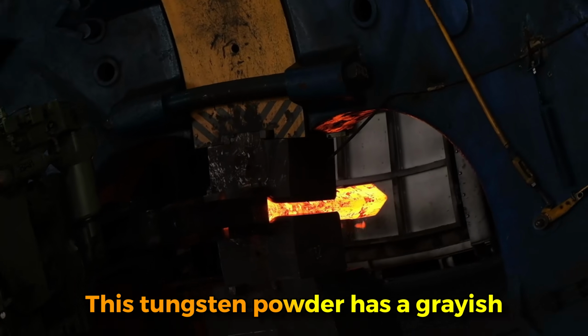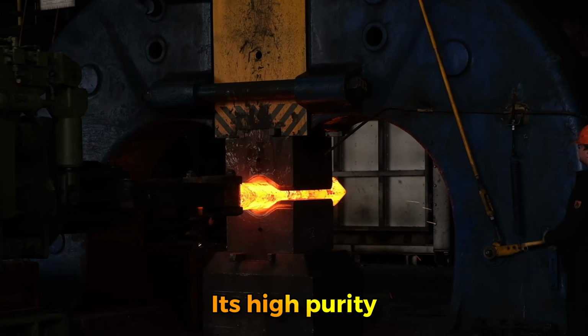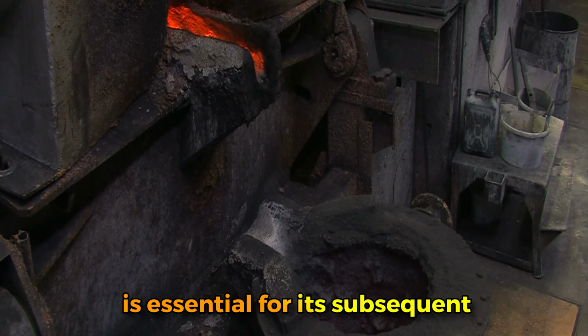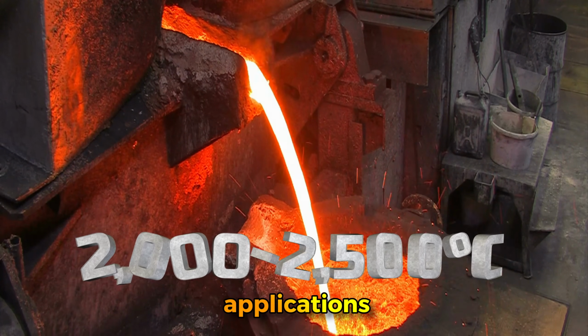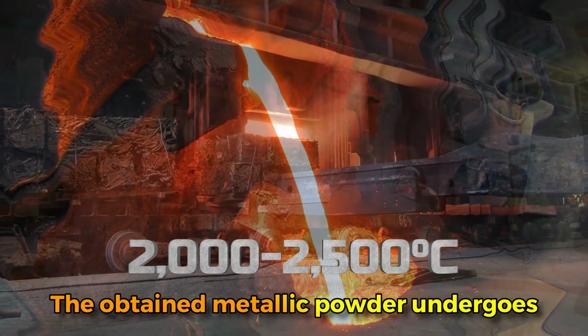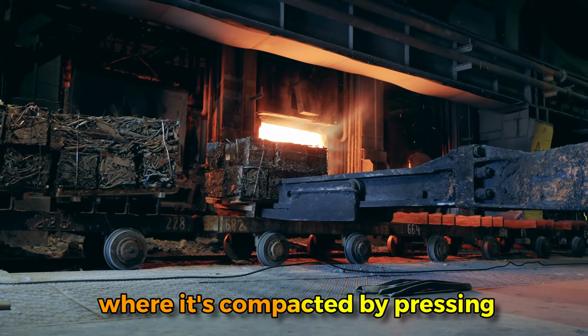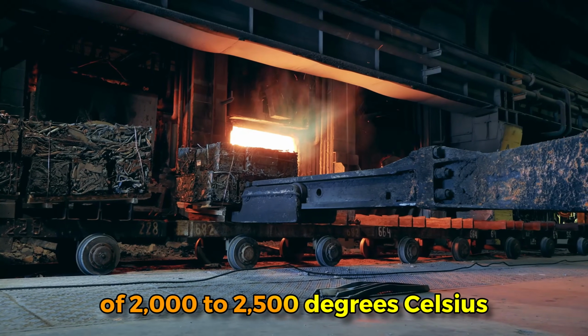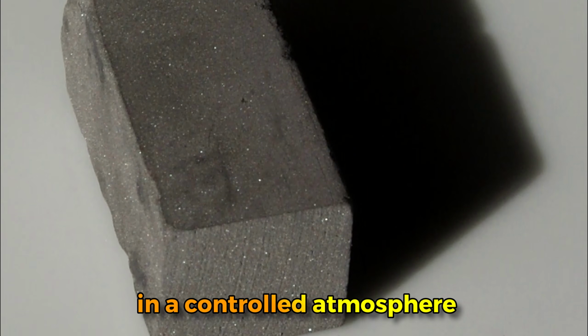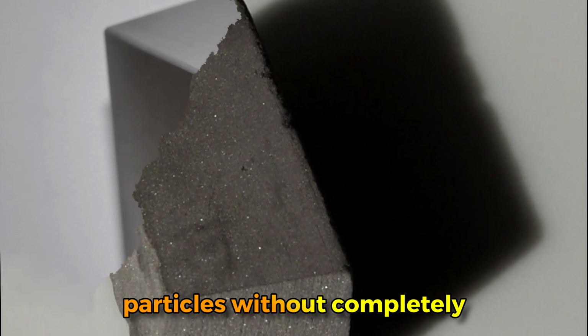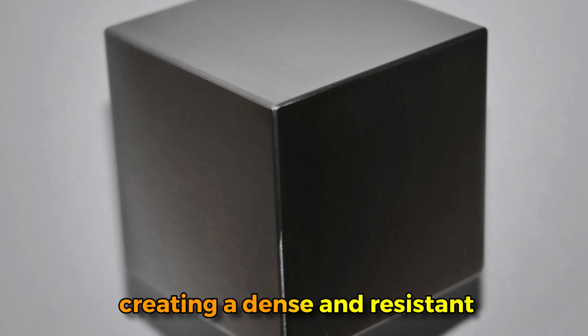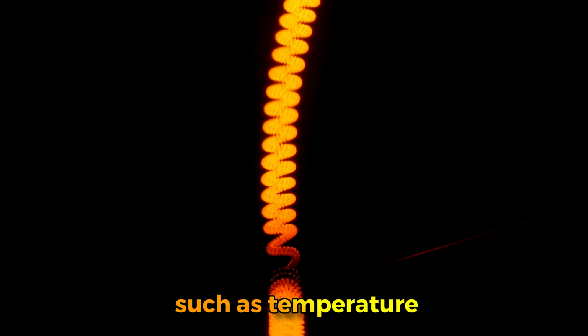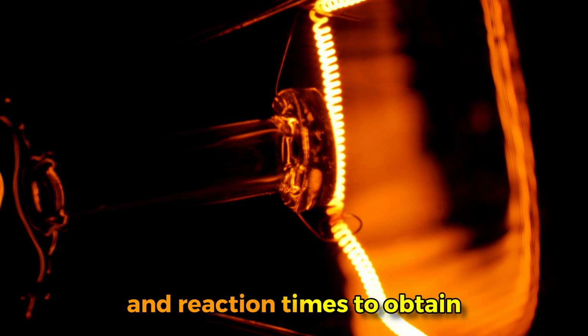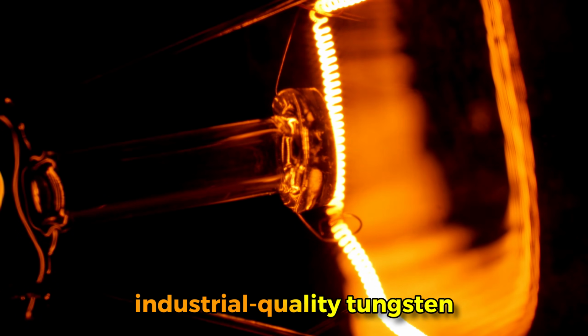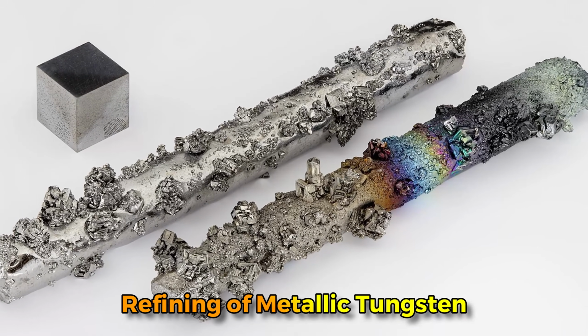This tungsten powder has a grayish appearance and crystalline structure. Its high purity, 99.9% plus, is essential for its subsequent applications. The obtained metallic powder undergoes powder metallurgy, where it's compacted by pressing and sintered at temperatures of 2000 to 2500 degrees Celsius in a controlled atmosphere. This treatment consolidates the particles without completely melting them, creating a dense and resistant metal. The complete process requires rigorous control of conditions such as temperature, pressure, hydrogen purity, and reaction times to obtain industrial quality tungsten. Step 6. Refining of metallic tungsten.